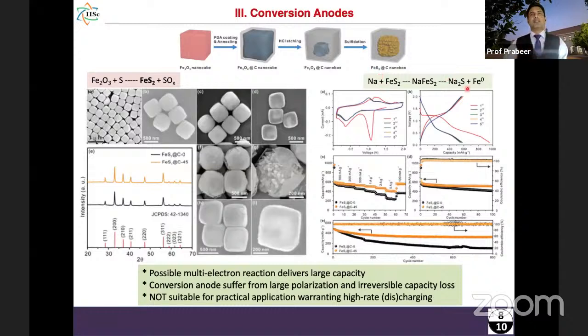So this is an example of how, using conversion reaction, we can get some capacity around 600 milliamp hour per gram, and it is fairly stable in operation. Now, one point to remember is, in case of conversion reaction, it is possible to have multi-electron reaction, which can deliver large capacity. Nonetheless, it is thermodynamically limited, and the conversion anodes suffer from very large polarization between charge and discharge, and also very high irreversible capacity loss. So very honestly, these conversion reaction anodes are not very suitable for practical application, particularly when we need high rate charge discharge operation.